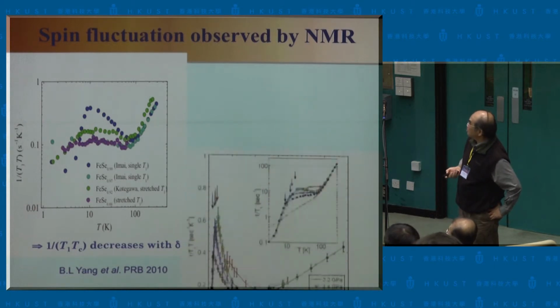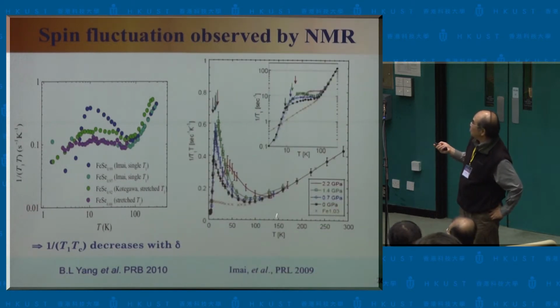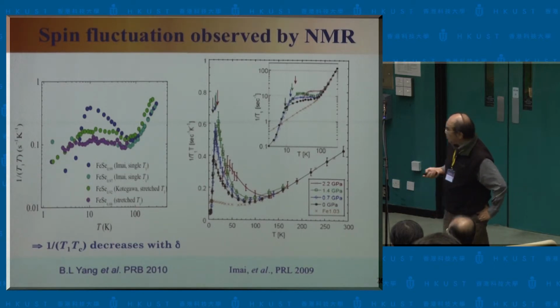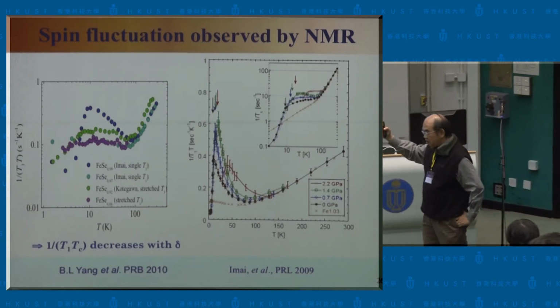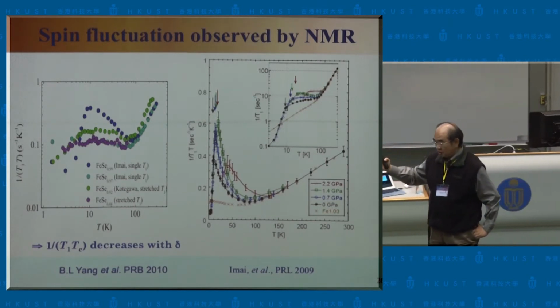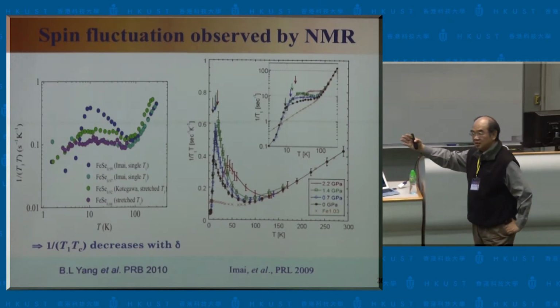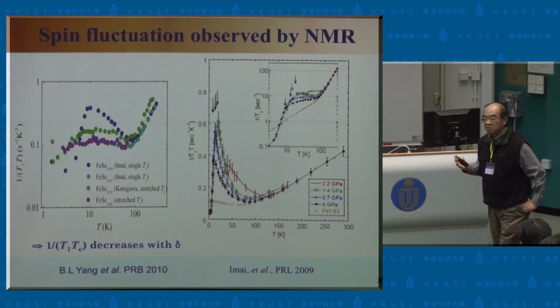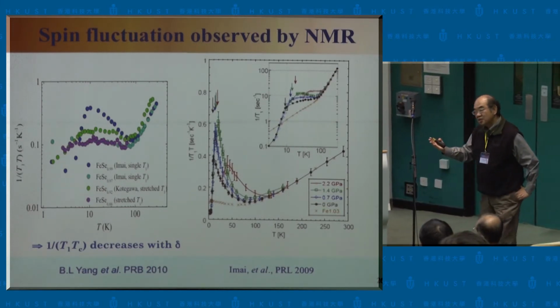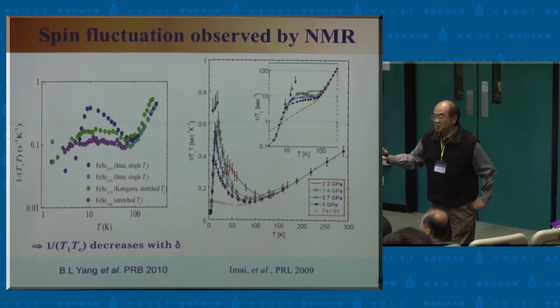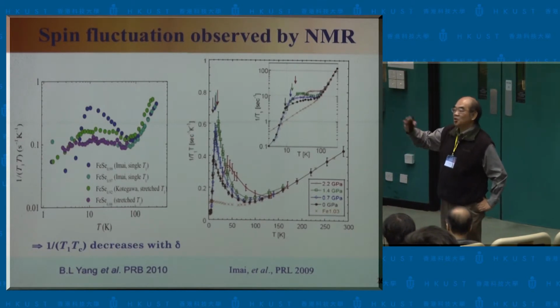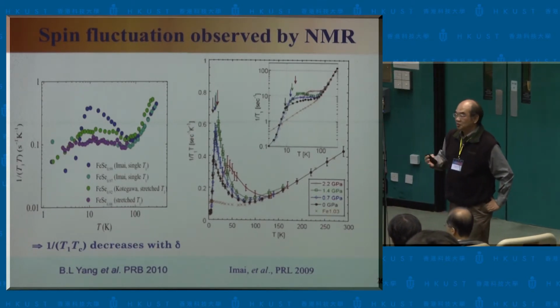Okay, we already know that there's a strong spin fluctuation associated with this superconducting one. I think the most beautiful data is from Imai's group, who even studied it under pressure and found that the pressure actually enhanced the spin fluctuation, associated with the Tc enhancement. So spin fluctuation is definitely associated with the superconductivity, and as I mentioned, that is also related to the structural transformation.